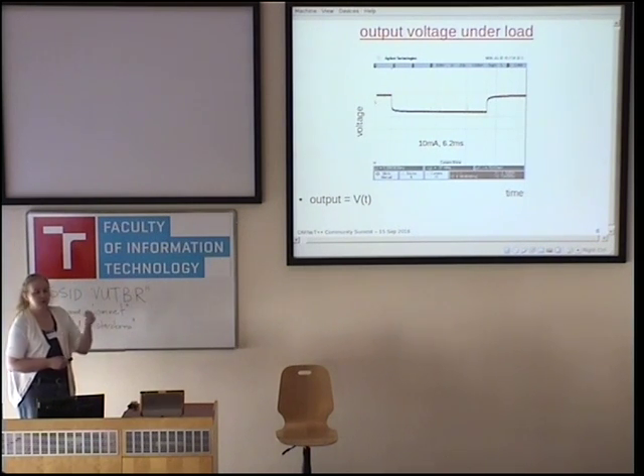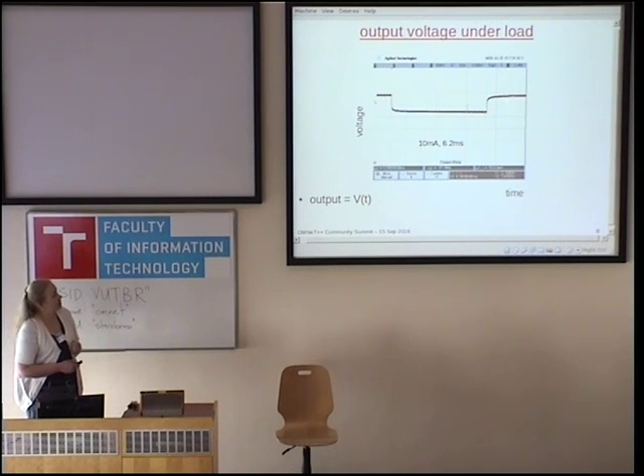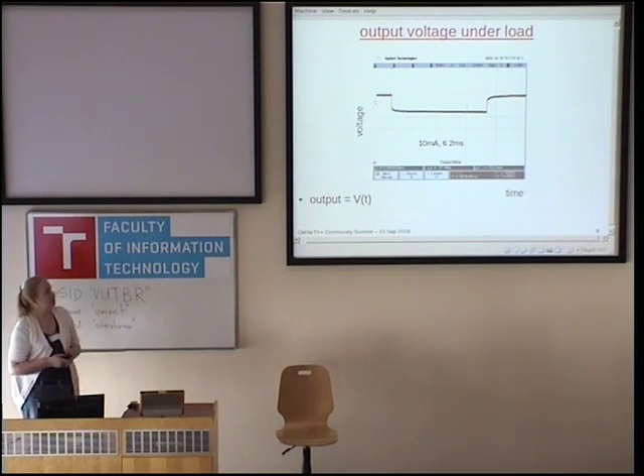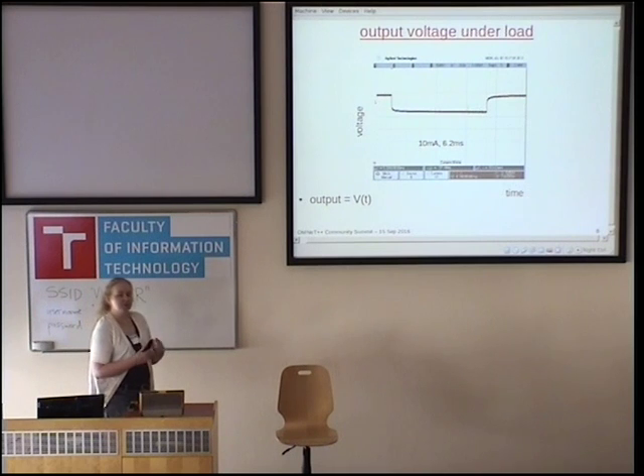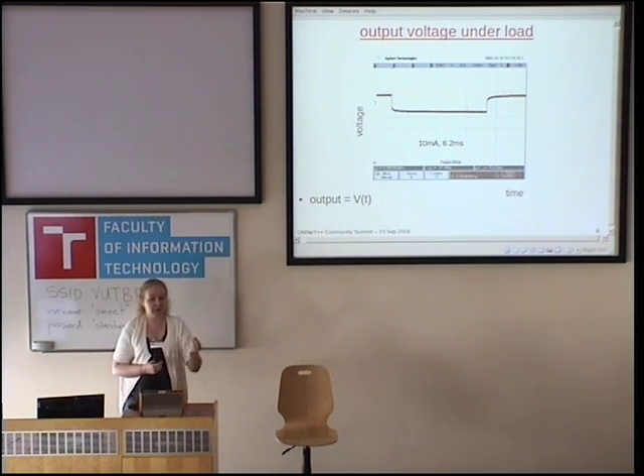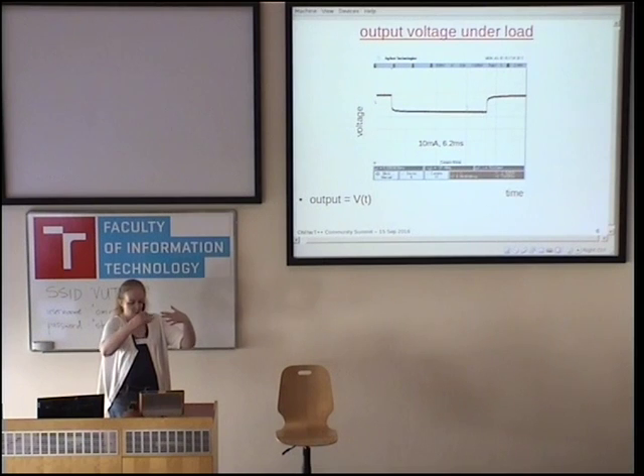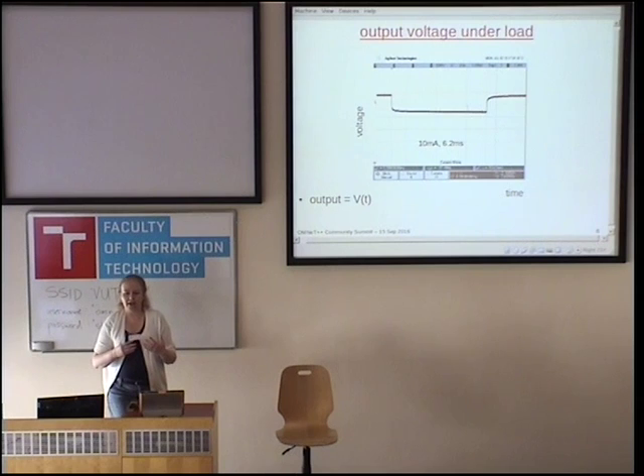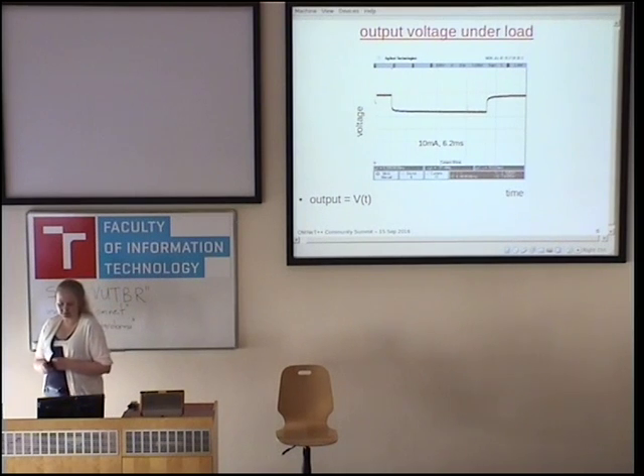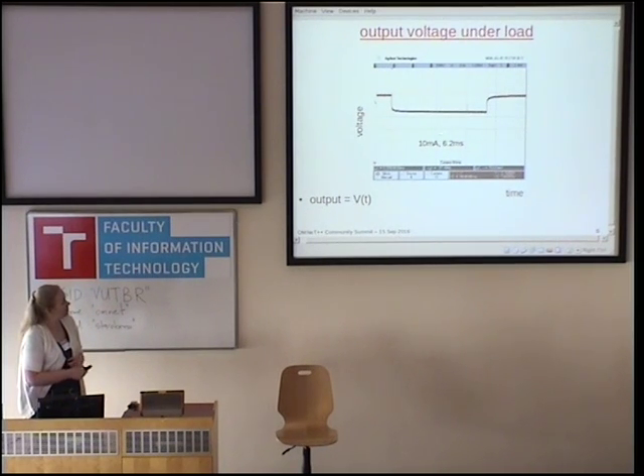At the end, the load is released. We get an immediate recovery — again, that's the internal resistance of the battery; we're no longer drawing current through it. And then we see that the voltage continues to increase for a while after we've taken away the load. What's happening is that the lithium ions are diffusing through the electrolyte while the battery has load being drawn; when the load is taken away, that diffusion process relaxes, and we get what's called charge recovery.